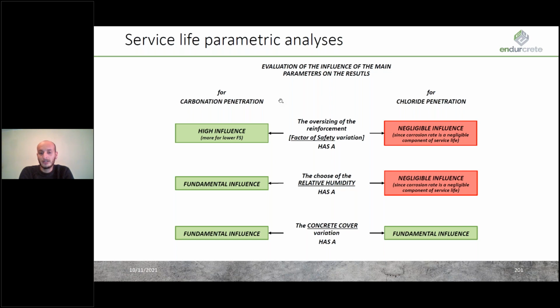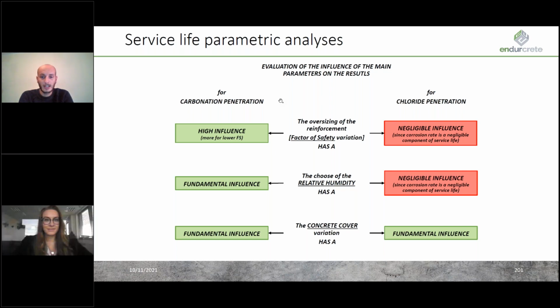So since the concrete cover is the main parameter that can influence the chloride penetration velocity, in this case it is the most important one. And so the concrete cover can be assessed as the most important parameter for both these types of attack on concrete, while for carbonation, all the different parameters have an important influence on the evaluation. And that's all for me, and thanks for your attention.